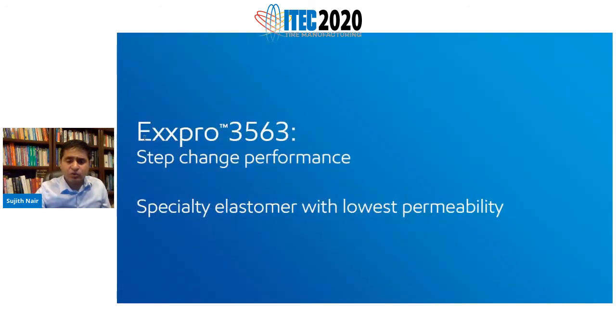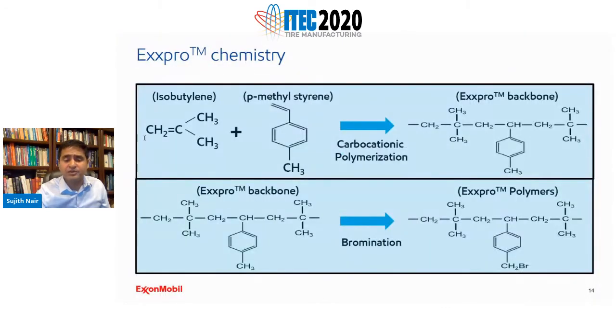So going into Exxpro, we'd like to say that Exxpro is probably the specialty elastomer available today with the lowest permeability. Looking at the chemistry of Exxpro, so again, butyl is basically a polymer that's made from isobutylene and isoprene. So it's basically an isobutylene co-isoprene polymer, right? In Exxpro, the difference is, instead of using isoprene, we replace that isoprene with something called paramethylstyrene. You do a carbocationic polymerization, you get the Exxpro backbone. So you see that big, bulky, pendant aromatic group there. That is the difference between bromobutyl and Exxpro.